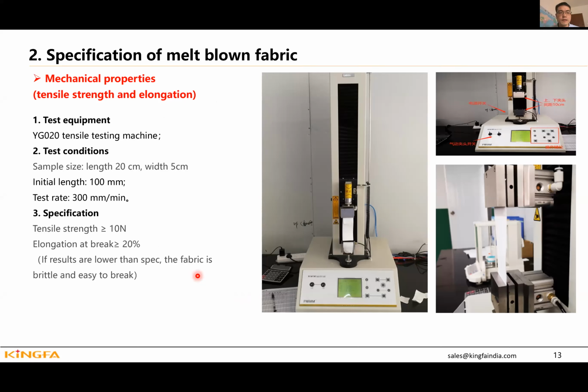The third part is the mechanical properties. When we use this fabric, it also has some tensile strength and elongation. We use this tensile machine to test the property. We cut the sample with scissors or a knife. The length is 20 centimeters and the width is 5 centimeters. Our specification for the tensile strength is more than 10 Newton. Elongation is about 20%. If our test result is lower than this specification, that means the fabric is a little brittle and very easy to break. So this is what we should test when we get this fabric.